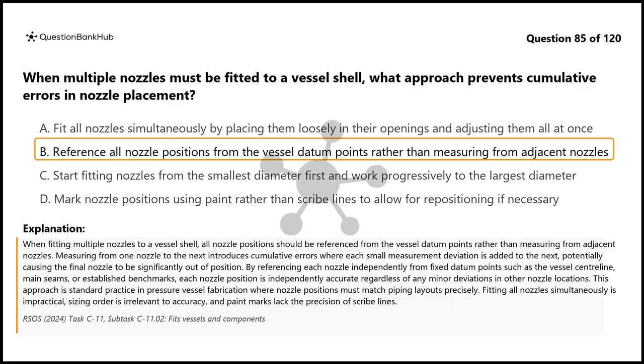By referencing each nozzle independently from fixed datum points such as the vessel centerline, main seams, or established benchmarks, each nozzle position is independently accurate regardless of any minor deviations in other nozzle locations. This approach is standard practice in pressure vessel fabrication where nozzle positions must match piping layouts precisely. Fitting all nozzles simultaneously is impractical, sizing order is irrelevant to accuracy, and paint marks lack the precision of scribe lines.